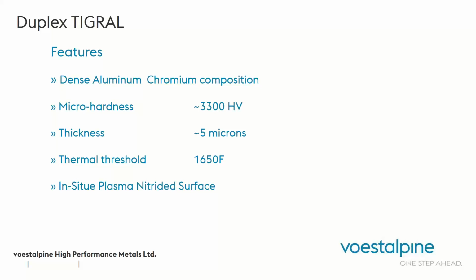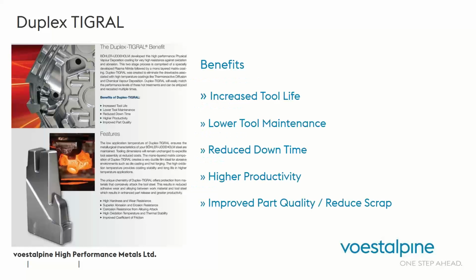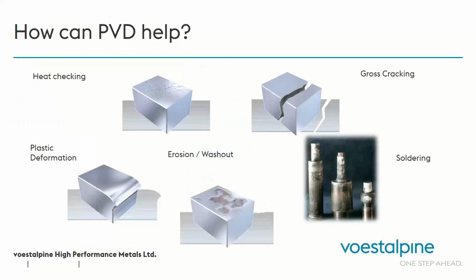Thermal threshold is 1650, which is well above your aluminum melt temperatures. And we have the in situ plasma nitride process that I indicated will help adhesion and support all of the actual coating film. But the benefits is what you're interested in. The benefits you'll see is increased tool life, lower tool maintenance, reduced downtime, which is absolutely critical in this age. And with reduced downtime, you do get higher productivity. And hopefully you should see improved part quality and reduced scrap, which is absolutely critical in any operation to keep your costs down. So let's see, how can PVD help?